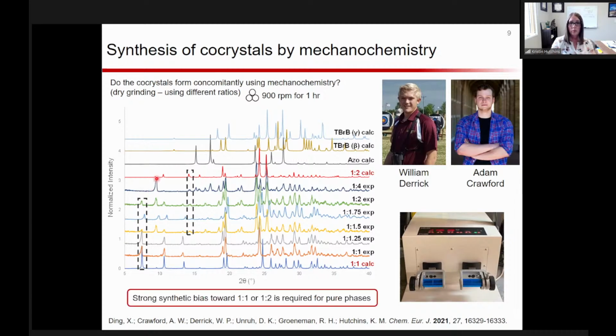So we have a little bit more control by mechanochemistry in getting separation of those 2 forms. We do get mixtures in those middle ratios, but using either 1-to-1 or a really strong bias towards the 1-to-2 allows us to get those 2 phases, where we couldn't do that in solution.